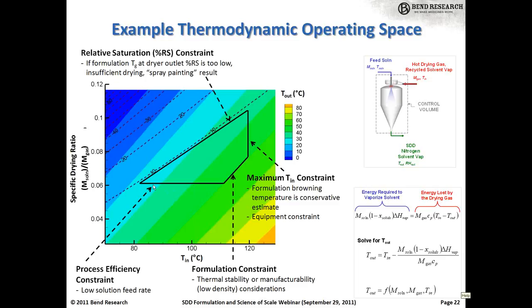Next, you can look at a process efficiency constraint. So at some point, if the solution feed rate drops too low, the spray drying process might just not be viable to progress to the next stage. So usually you have a lower limit on how low you're willing to accept in terms of feed rate. Another constraint is a relative solvent saturation constraint.